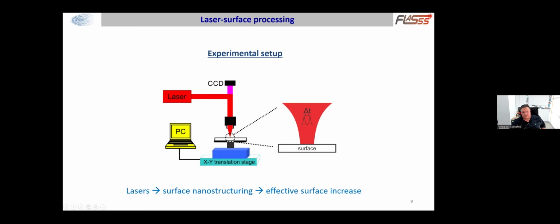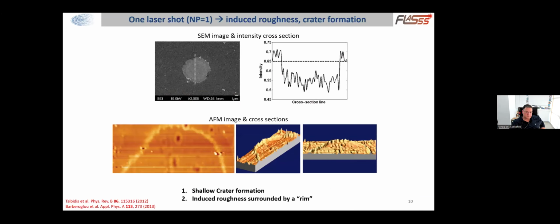So now we'll start a small parenthesis in order to say a few words about the background of laser matter interaction, and in particular laser surface nanostructuring. So consider that you have one laser shot shining onto a metallic surface, or any surface in general. If the energy is enough, we have the removal of material from this surface, and a shallow crater formation in this case, as you can see in both the SEM images and the AFM images. And this is confirmed also by the intensity cross sections, when we look at the profiles of this interaction.